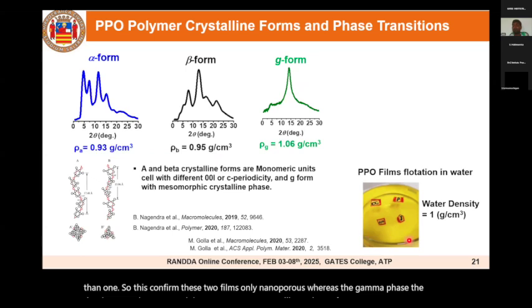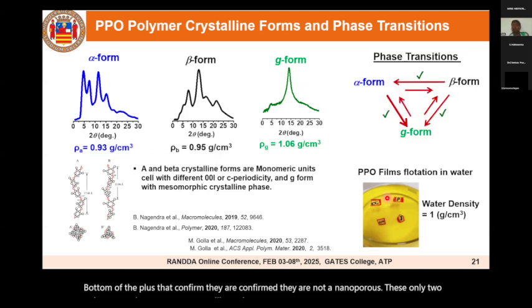You can see alpha and beta float on the surface of the water, whereas the amorphous and the gamma phase sink to the bottom of the flask. That confirms they are not nanoporous. Only these two are nanoporous crystalline polymers. And also we studied the phase transition among the three crystalline phases.